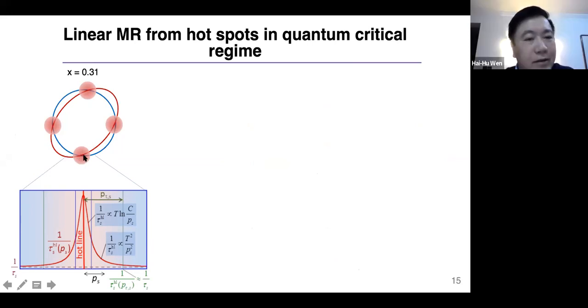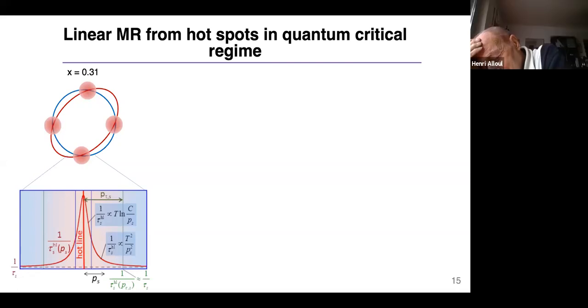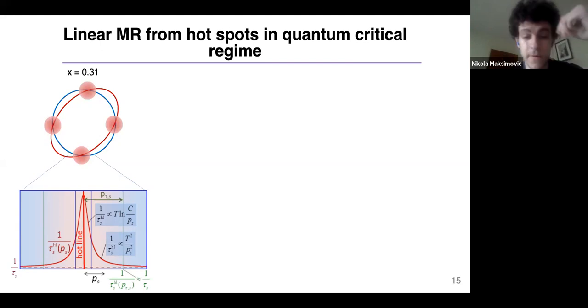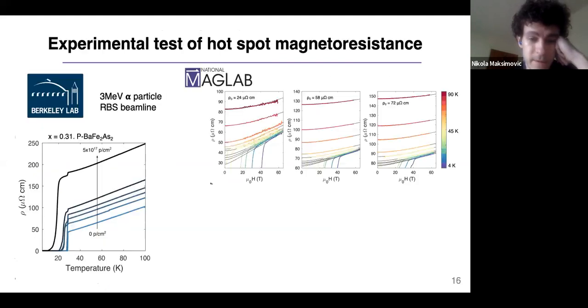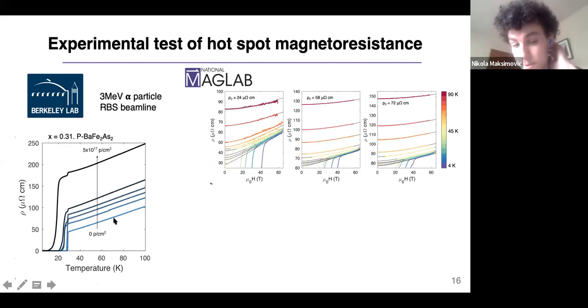I see. So does this scanning result have any relation to the superlinear resistivity? I mean the temperature dependence. It's difficult to say. This is one of the main questions, whether you can recover the temperature dependent resistivity based on this hot spot and cold spot model. I don't think there's a good way to do that at present. In our work, we're not able to capture the temperature dependent resistivity. I see. Okay.